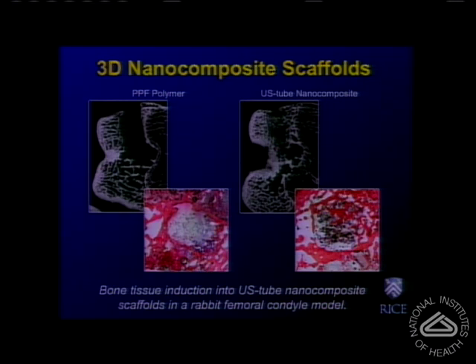To our huge surprise, when nanocomposites of ultra-short carbon nanotubes were implanted in the same defect, we saw tissue ingrowth within the pores of the material, as shown here in the microcomputed tomography image and also here in the histological section. This was totally unexpected, something that was validated by further studies in our laboratory and other laboratories that show the tissue inductive properties of nanocomposites. Although the phenomenon is very reproducible, the molecular mechanism is still under investigation.